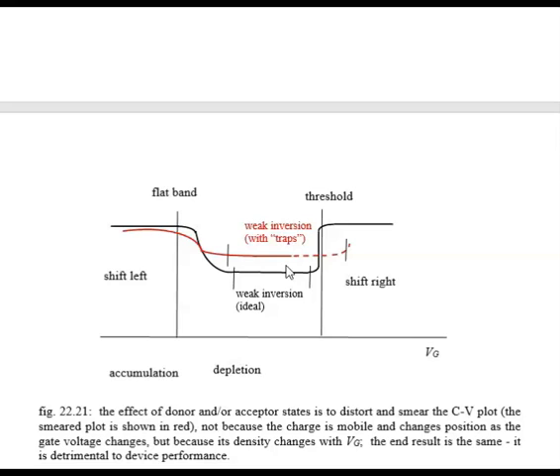Well, people said, okay, these are dangling bonds. How do we undangle the bonds? Let's put a molecule, not a molecule, an atom in there, which can attach to those bonds. So what people do is an anneal, a high temperature process, where they put in hydrogen gas, and the hydrogen attaches to any dangling silicon bonds. And what we find with the hydrogen anneal is that the red curve goes back to the black curve, and that is how this problem has pretty much been taken care of.